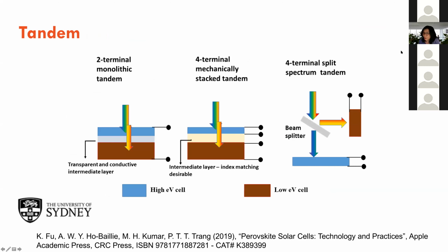Okay, so with the tandem, there are different ways of making tandem solar cells. Either you can directly deposit the high band gap cell onto the bottom band gap cell with some sort of intermediate layer. And this is what we call the monolithic tandem. Or you can stack two cells together, just mechanically stack them, put one on top of the other, and then you can have some sort of medium there just to reduce the optical loss. We call it mechanically stacked, and it's 4-terminal because you have a pair of wires coming out from each cell. Or you can even use some optical element, for example a filter, to reflect the low energy light onto a low bandgap cell, and then high energy light onto a high bandgap cell.